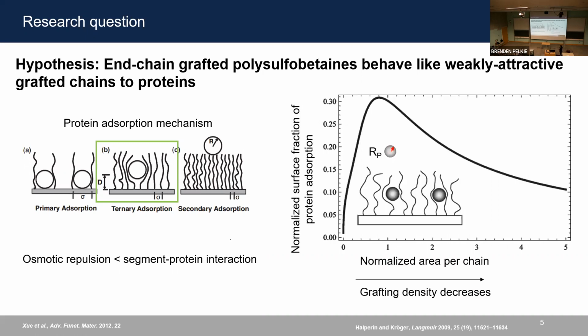So for this scenario, Halperin and Kroger, in this paper, developed a theoretical model that showed that if you plot the normalized surface density of adsorbed protein as a function of area per chain, or the grafting density, then the adsorption profile is bell-shaped rather than monotonically decreasing. So what happens is that at both ends, when you have a highly dense brush or an isolated mushroom-like coil chain, the adsorption is low, but at an intermediate surface density, which corresponds to a weakly overlapping chain, the protein adsorption is the highest.